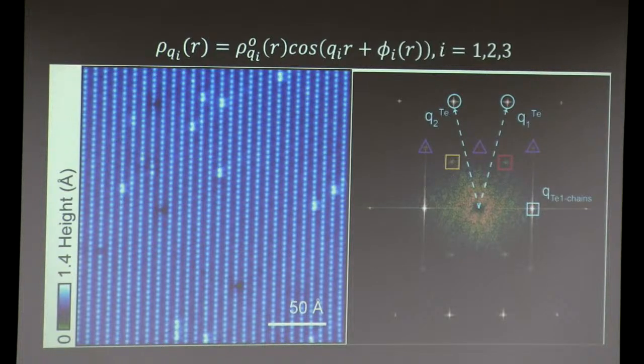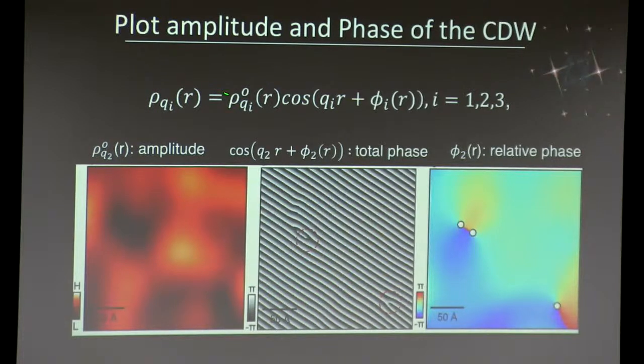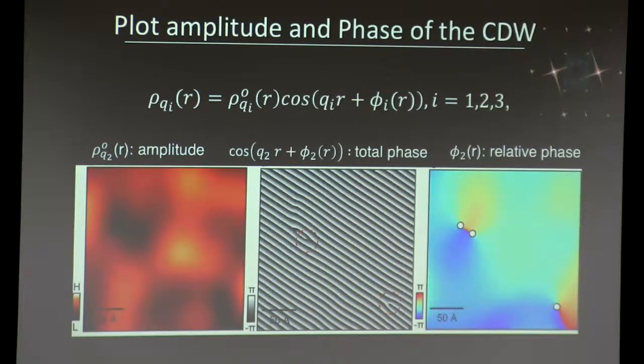Fortunately, we have access to all of this through the Fourier transform. So what we can do is take a Fourier transform, and by looking at the charge density wave peaks, we can extract the following information. We can extract the amplitude of the CDW order parameter. We can extract this cosine QR, which is the oscillatory part of the charge density wave, plus any phase slips. If there are phase slips, we'll extract that as well. And finally, from this map, we can also extract the relative phase, which should show you any point dislocations in this field of view.